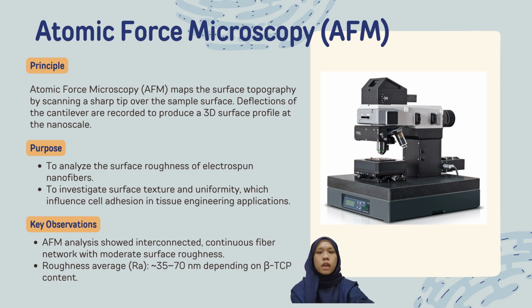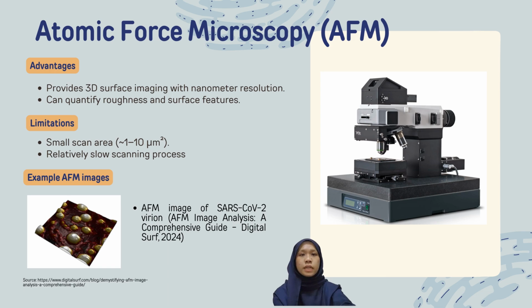The key observation for AFM is the analysis shows an interconnected continuous fiber network with moderate surface roughness. Roughness average is about 35 to 70 nanometers depending on beta TCP content. The advantage of AFM is it provides 3D surface imaging with nanometer resolution. It can quantify roughness and surface features. The limitation for AFM is small scan area, about 1 to 10 micrometers squared, and a relatively slow scanning process. These are examples of AFM images.